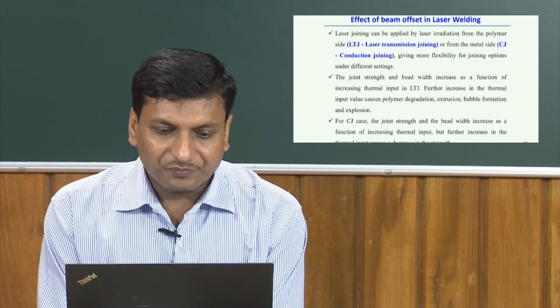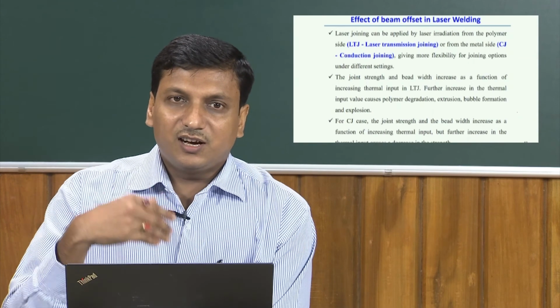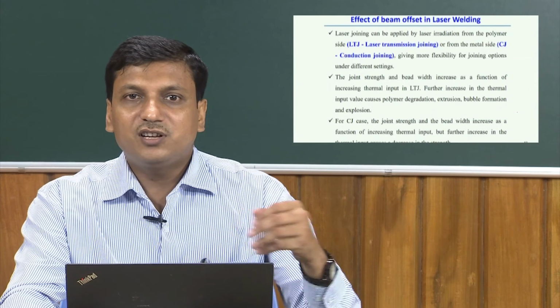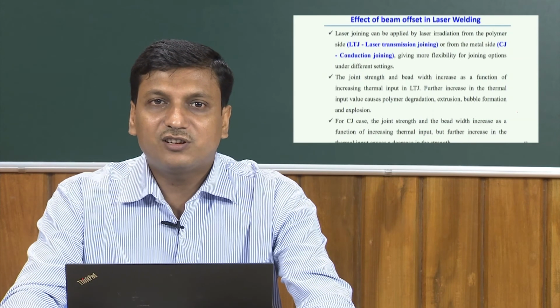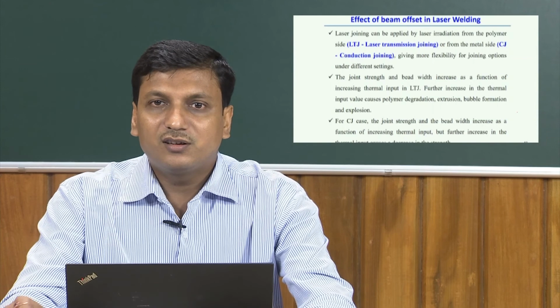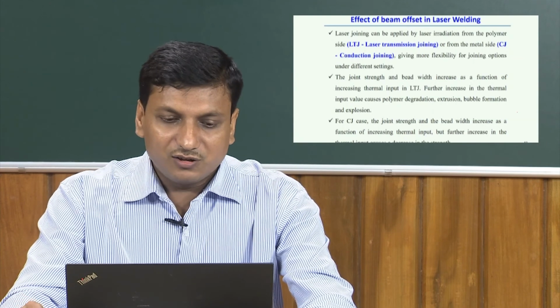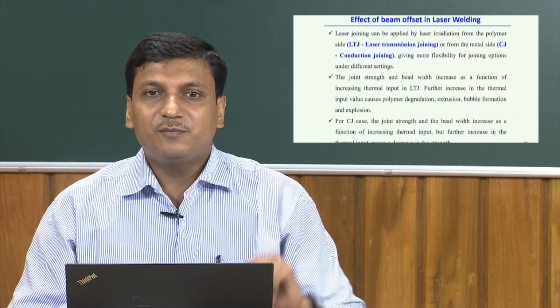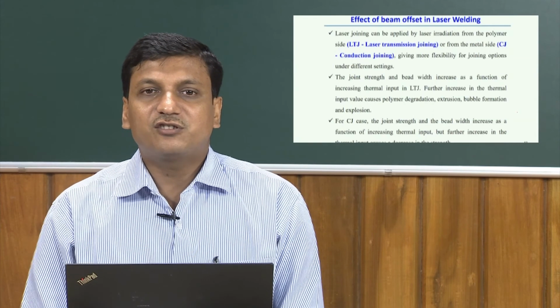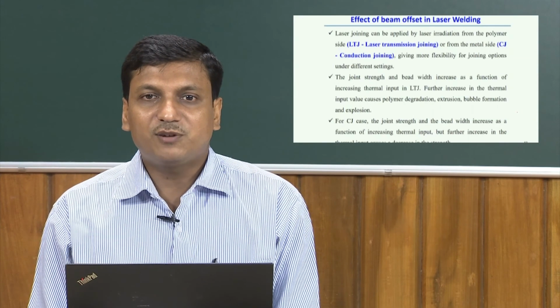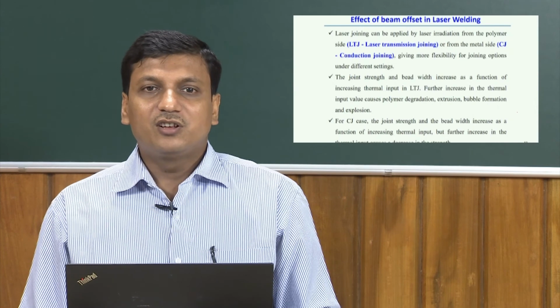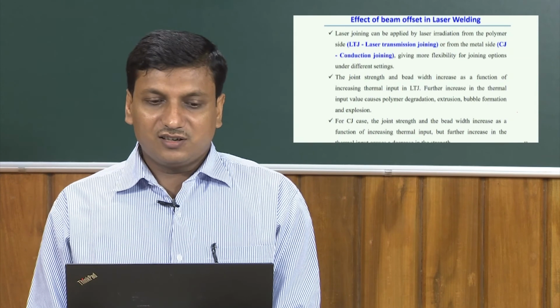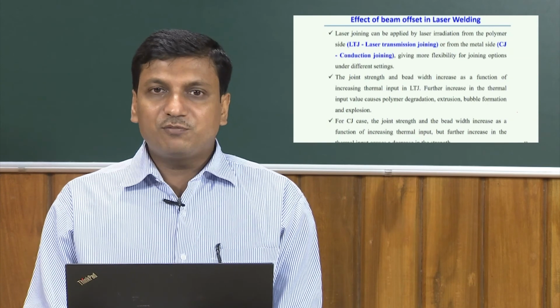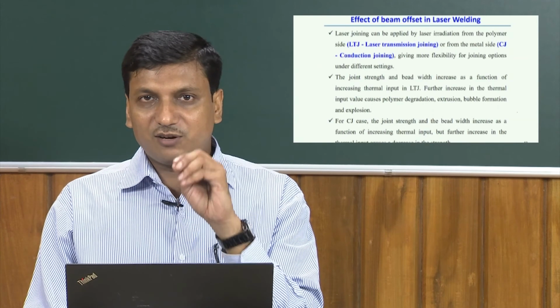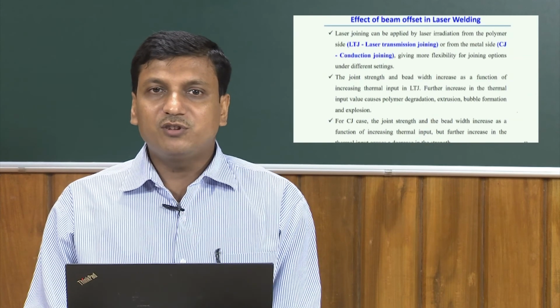On one side it is called laser transmission welding, but from the other side it is called conduction joining, or conduction welding. In this case, the joint strength and the bead width also increase as a function of the increasing thermal input, but a further increase in the thermal input causes a decrease in the strength. So, some optimum amount of thermal input is required to get a good joint between the metal and the plastic.